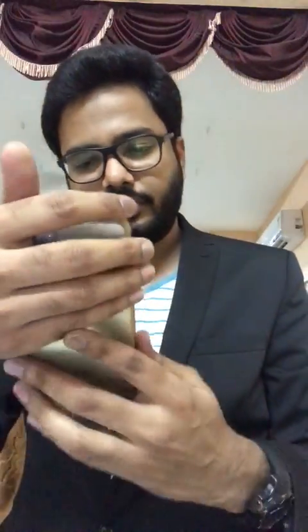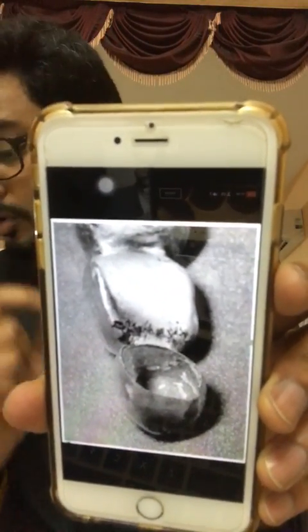So in the image, if you see, it's an FPD, right? The porosity in the pontic area is caused by the ability of the pontic to retain heat because of its bulk and because it was located in the center of the ring. This problem can be solved by simply attaching one or more small 18 gauge sprues at the surface most distant from the main sprue attachment, right? So to overcome that, what we do is we attach multiple sprues wherever necessary, and the sprue has to be 18 gauge, and this is called chill set sprues.